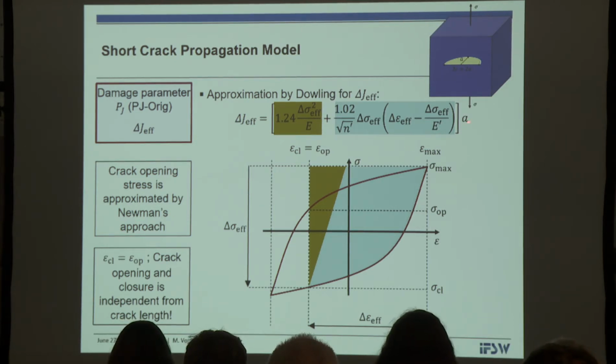So there are two factors, a crack length related factor and a factor from mechanics which does not contain any crack dimension, and we call that in brackets a damage parameter, similar to the Smith-Watson-Topper damage parameter, and we call that P_J, and it's based on a cyclic version of the J integral. And these two components here can be attributed to strain energy densities in the uncracked situation, as shown here in these colored lines.